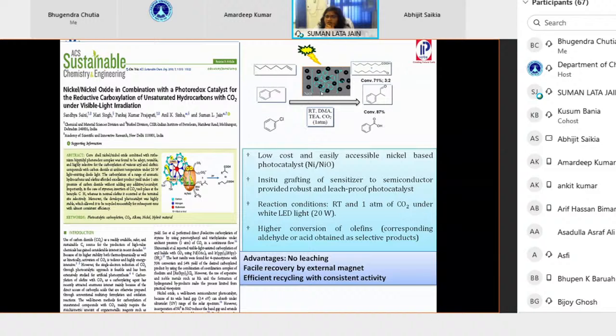So what are the main advantages of this? Here we use the nickel-based catalyst. However, in the literature, rhodium, that is an expensive metal, is used, so this was a cost-effective material that we developed. We immobilized the complex with the ruthenium sensitizer in situ, and attachment of this inhibited the leaching. In the previous report, where the rhodium-based complex and the ruthenium photosensitizer are used, both are in the homogeneous condition, so the recovery is not very easy.